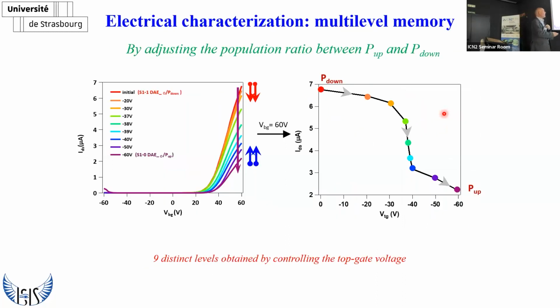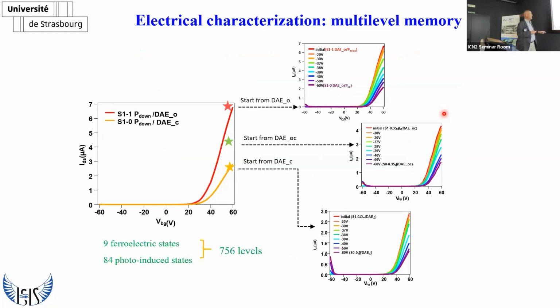Now you can also apply voltages that are just above the coercive field, and you can have a different number of dipoles that are oriented, and you can assess here 9 distinct levels. So essentially, if you combine the two stimuli, 84 times 9, you can have 756 different levels that you can assess. And actually, they are pretty robust. In their own states, the diarylethene we demonstrated can last for over 2 years, and the ferroelectric is something that was already demonstrated to be very robust.